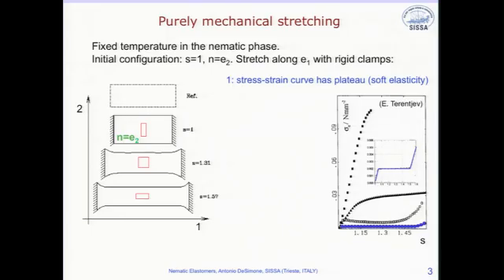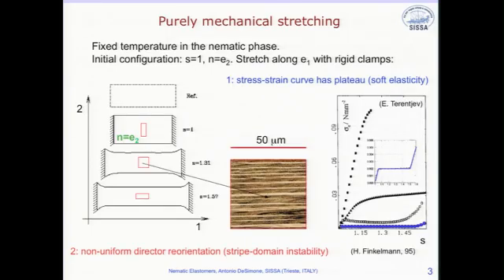Now, this is a liquid crystal, so there's an optical trace of this behavior, and here is the optical trace. If you look at this material, you will see optical patterns, and in fact, it's more interesting than what I was suggesting before, because you see bands. Bands that are alternatively transparent and opaque, signaling the fact that there is a texture, there are bands of director, okay? And so as you will see, this is due to the fact that the rotation of the director is not homogeneous, but it happens in domains, okay? And this is called the stripe domain instability in the literature.